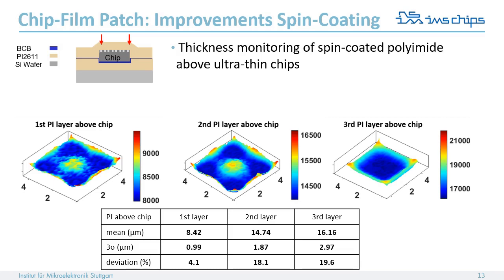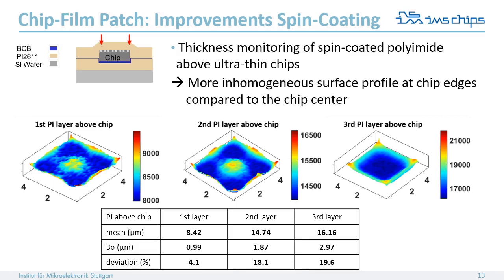A more inhomogeneous polyimide surface on the chip edges is observed, and this will lead to an inconsistent etching profile during the opening of the small chip pads and consequently to polyimide over-etching. On the other hand, thickness deviation in the chip center tends to be more uniform with each additional applied polyimide layer above the chip. The recent findings can be transferred and integrated in future chip design, where the chip pads may be located inwards near the chip center to avoid over-etching.